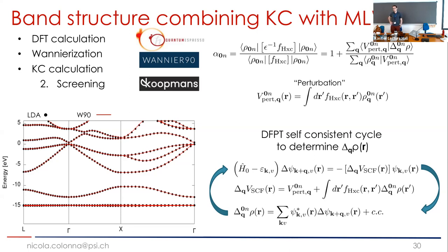I think we have only one case where we looked at this, some of the DNA and RNA bases. And that term was giving the right torsion of a certain angle. But it's not that we expect particularly exciting results from the total energy and thus the phonons. Apart from the fact that you have consistently in KIPZ a screened Fock exchange that at the end is the same thing that hybrid functionals in different flavors give you. So that might also be good. The path of the derivation is not the change of the total energy functional, and thus you expect that the response of the functional is the same. For KI it is absolutely the same, and KIPZ would be similar to a hybrid with just a different flavor of screened Fock exchange.